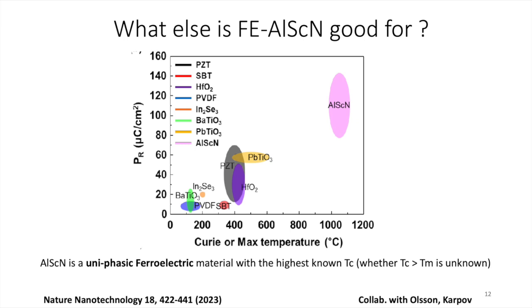So up to 1100 degrees Celsius, we have not seen ferroelectricity being lost in this material, which is remarkable. Right, and on top of that, it's a thin film material, which means you can put it down on silicon wafers or any other wafers and actually make devices out of it. And the reason I think this is very stable is because of its highly polar character. It's a wurtzite crystal structure. Wurtzite crystal structures are very thermodynamically stable. And so the bonds are so strong, so ionic, that it doesn't feel the need to exist in any other state other than the ferroelectric state up to extremely high temperatures, right?